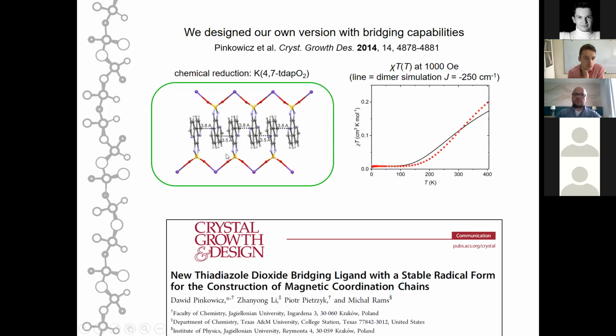So here is the structure of the potassium salt of this compound. You can see that indeed this 4,7-phenanthroline dioxothiadiazole can form pi stacks, and the SQUID magnetometer measurements, depicted as chi-T versus temperature, show that there are very strong magnetic interactions in the system. We only managed to simulate this behavior by using the dimer approximation, and it appears that this interaction should be on the order of minus 200 wave numbers through the pi stack interactions.